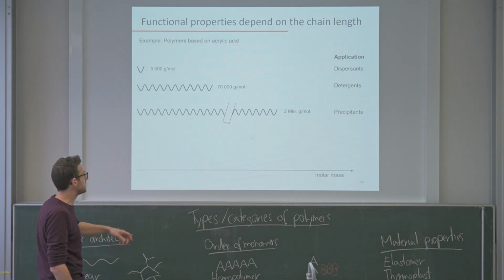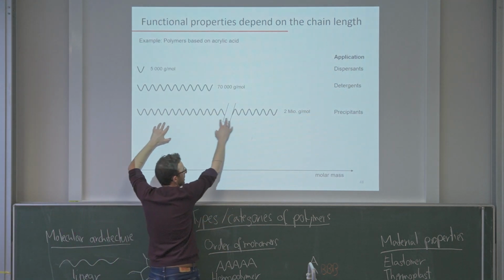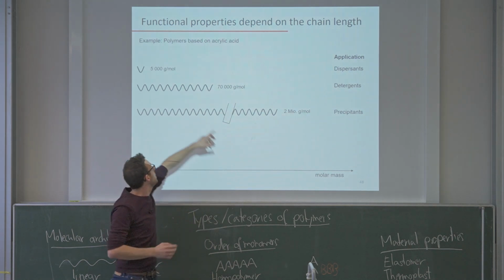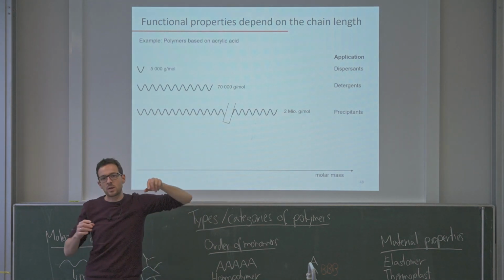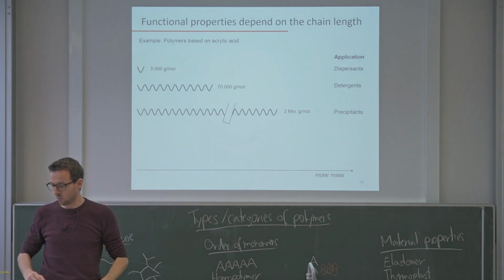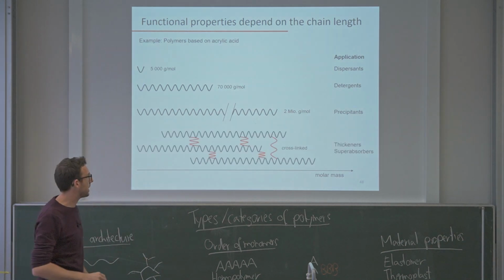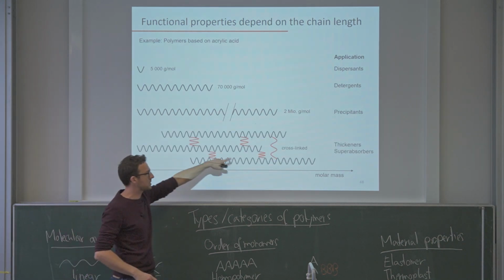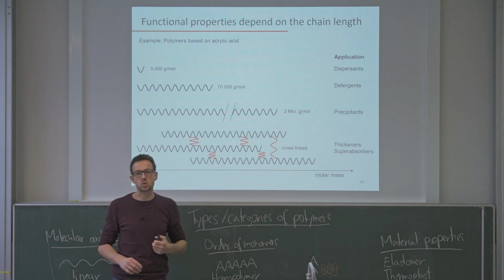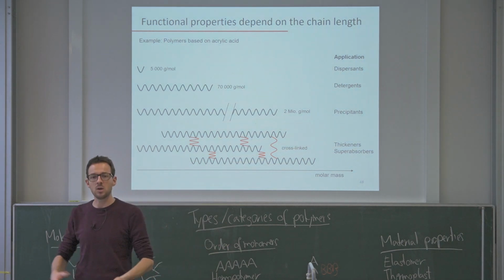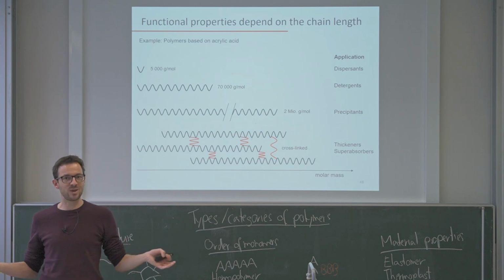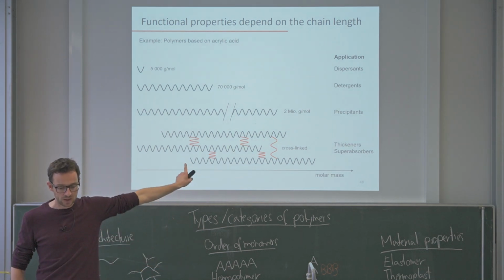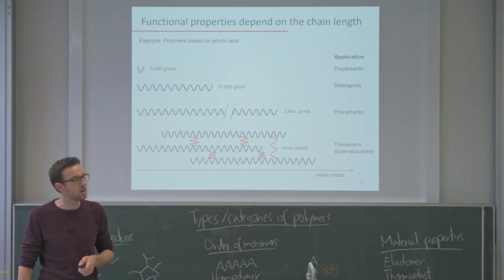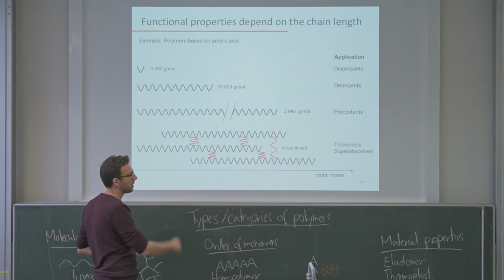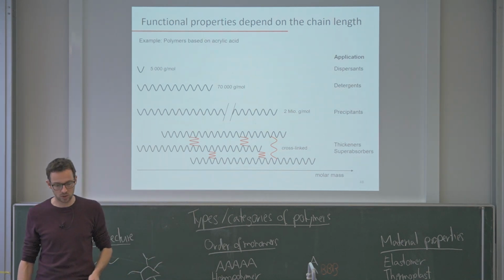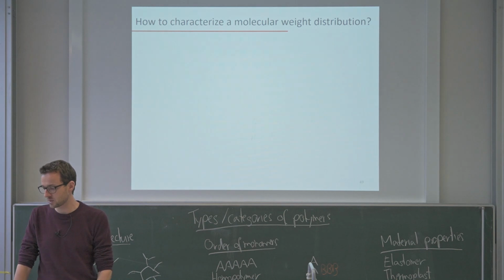This has a lot of charges. Here you connect multiple particles, so they become bigger and bigger. Here you add them on the surface of the particles, so they get more charged and therefore more stable. Now if you take this material and you add some crosslinks, then you have a superabsorber. Now you use it in a diaper to soak up water. So you see very different fields of applications with exactly the same polymer, and the only difference is the molecular weight. And this is why it's so important to understand this and to know this.